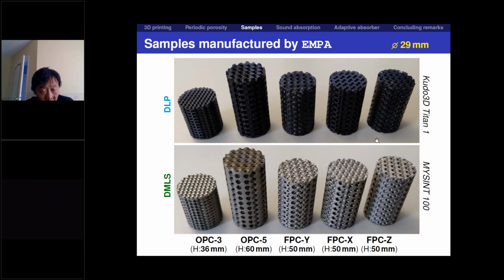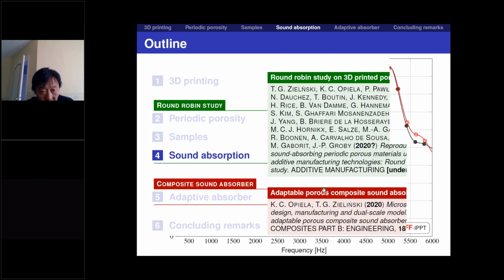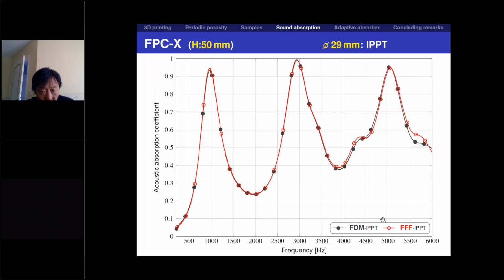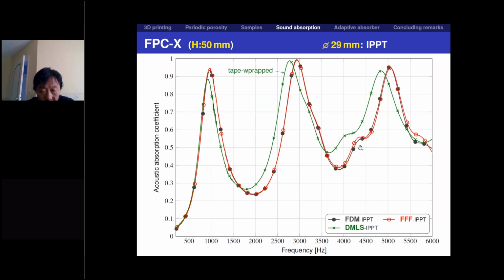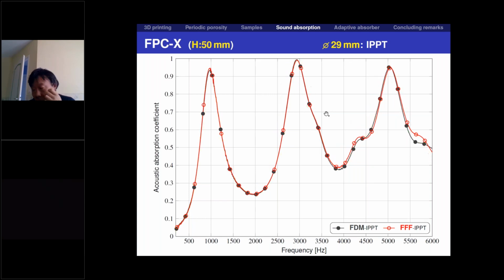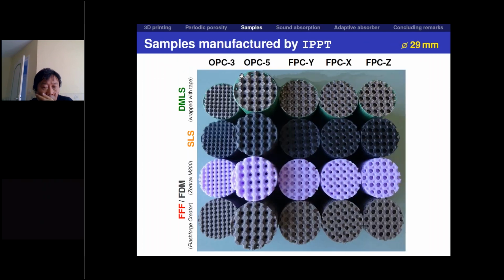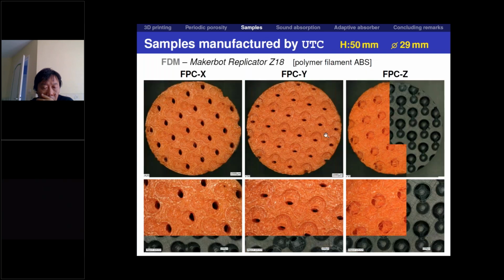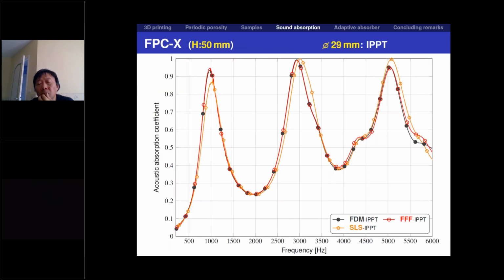Finally, the results from Switzerland, resin samples and metal samples, and the results of sound absorption. These are two curves manufactured using FDM technology, but different printers. I was quite astonished seeing that they are very similar, but when I compared them also with the curve for samples manufactured from polymer powder, you also see that the curve is very similar, although the technology is completely different. And then you have a curve for the metal sample, and you see for these two peaks at higher frequencies, we have some kind of shift to lower frequencies, and this is because these samples were wrapped in a tape in order to avoid scratching the inside of our impedance tube.